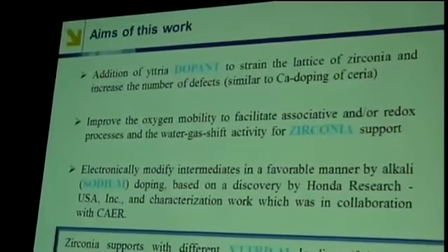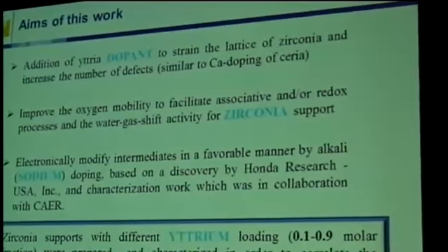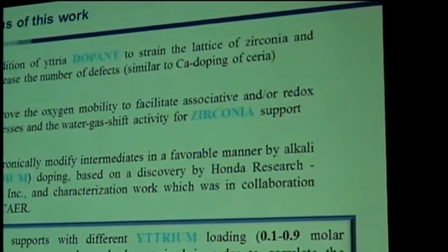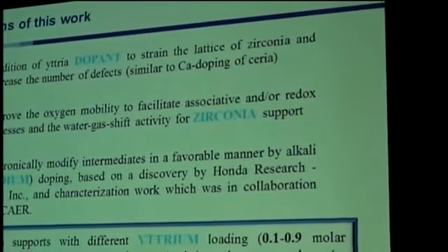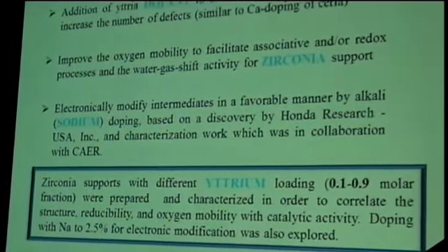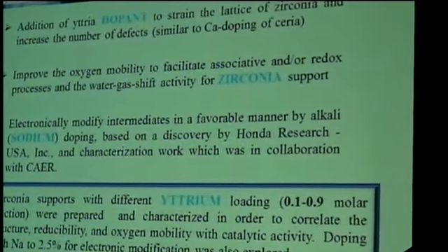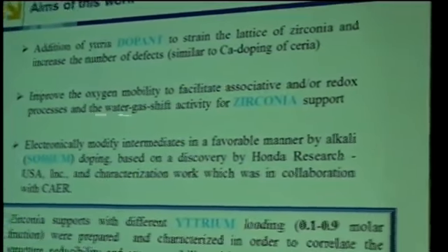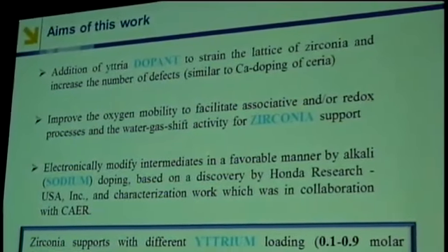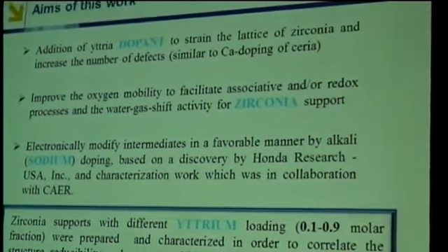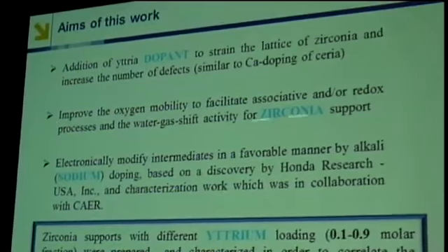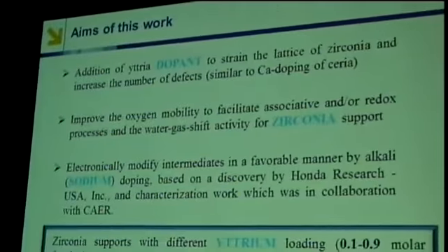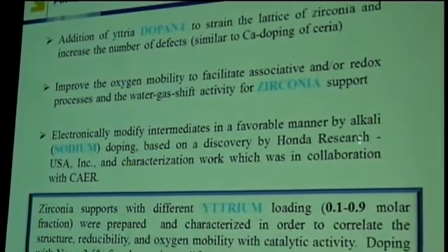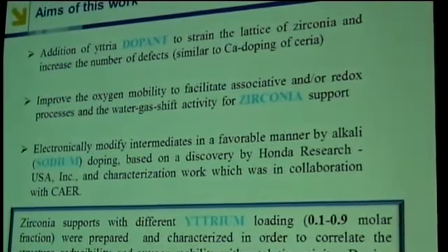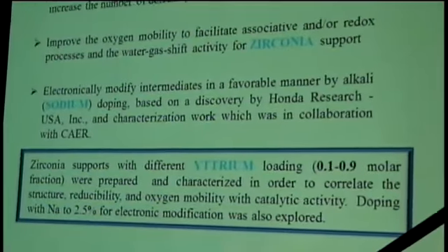So the aims of this work are how can we improve these kinds of catalysts? And we've been working a bit with zirconia over the last several years off and on. And one idea is to dope yttria into zirconia, where we're replacing zirconia, which is +4, with yttria, which is +3, and then to maintain charge neutrality, you have oxygen vacancies introduced into the catalyst. Another possibility is, since we have oxygen adatoms involved in the redox mechanism, and we have adsorbed intermediates which are bound by oxygen to the surface, we might be able to strain the zirconia such that we improve the oxygen mobility. And then the other idea is to use electronic modifiers, such as alkali metals, to electronically modify the intermediates in a favorable way.